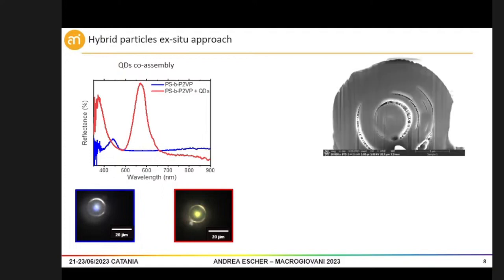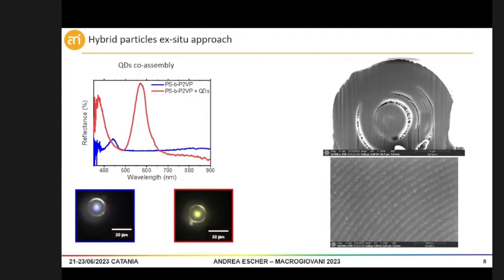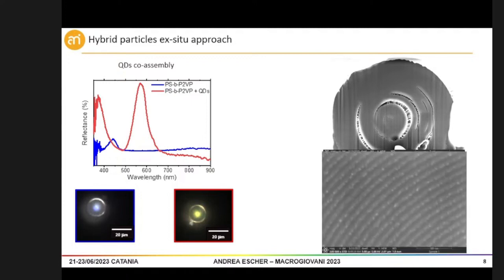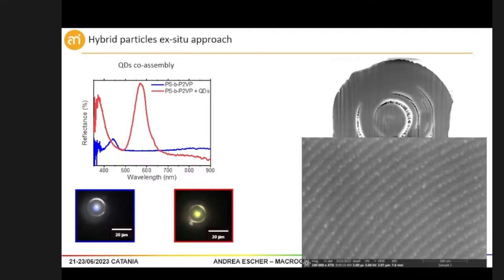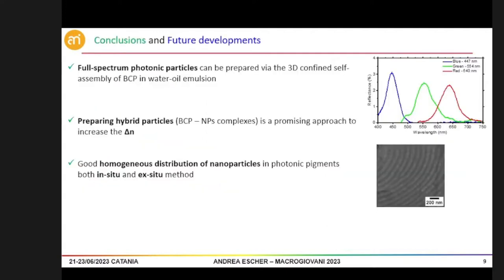And finally, I report also for this case the TEM image, and we can see that we have a very good homogeneous distribution of quantum dots inside the polymer domain. So in conclusion, I obtained a very large spectrum of photonic pigments that go from the violet to the red range in the visible light.